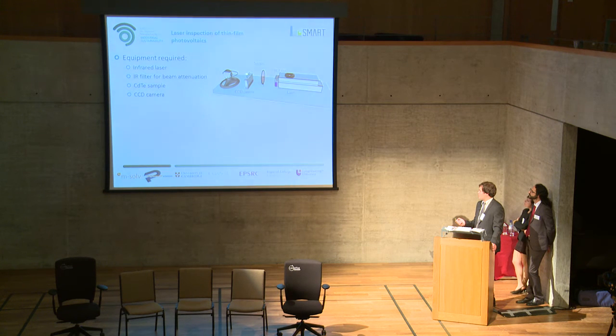So for this, we require a certain amount of equipment. We need an infrared laser, then an infrared filter, which is just used to control the output of the laser beam so it doesn't overload the camera. We have a cadmium telluride sample, and then we have a CCD-based camera itself, which is the experimental setup shown here. So the laser fires the beam through the IR filter, through the sample, and then into the camera. And that produces an image that looks like this.